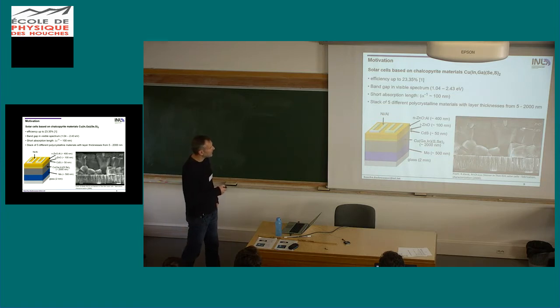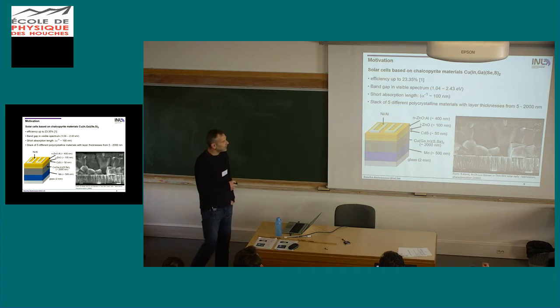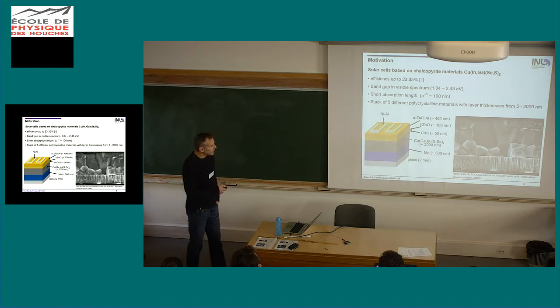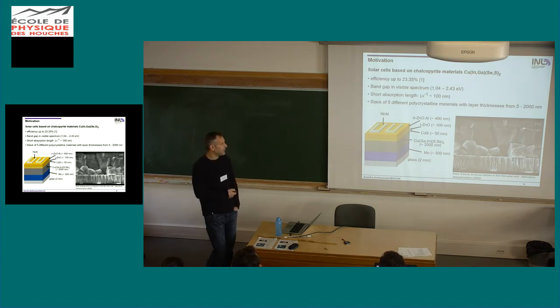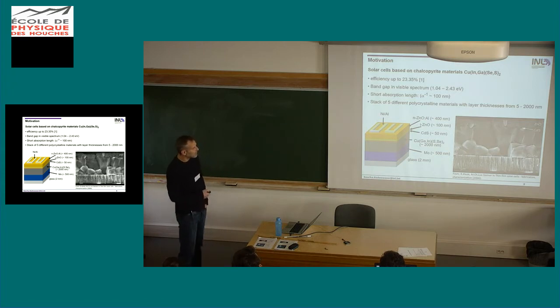And a typical solar cell consists of 5 different polycrystalline materials with different thicknesses. So we have molybdenum as a back contact, then the absorber layer, typically about 2 microns thick, a buffer layer, cadmium sulfide, and a zinc oxide window layer, which is actually a double layer here. And then at the interfaces, there are sometimes other materials that develop, for example, molybdenum selenide. We also heard this yesterday, I think.